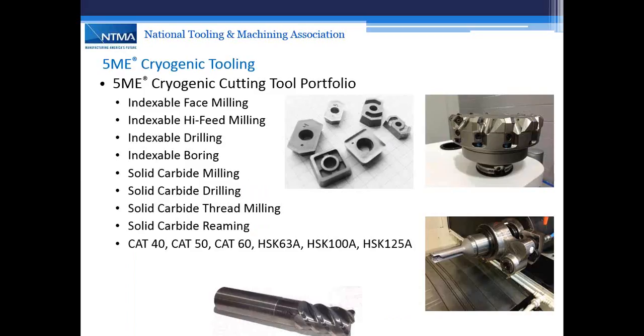Types of tools. We've done indexable face mills anywhere from 2 inches to 12 inches. There's really no limit there. And as you can see in the picture of the inserts, the front and the back, we actually press cavities in the back of the inserts to give the liquid nitrogen a place to sit and flow and be able to extract the heat from the cutting edge. And when it exhausts on the undercut furthest away from the workpiece, again, we're not trying to get the workpiece cold. We've done high feed mills, indexable drills, indexable boring tools, solid carbide end mills, drills, thread mills, and reamers. Interfaces: Cat 40, 50, 60, and HSK 63, 100, and 125.